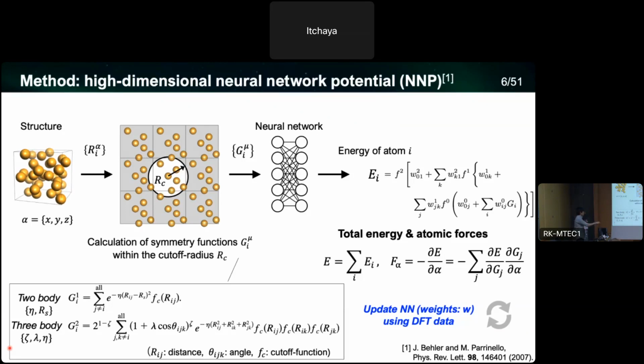And as you can see, in these functions we have several parameters like eta, lambda, zeta, and these indicate the decay factor or peak position of the functions. So we prepared different sets of parameters, and we finally get a set of different numerical values, which can be given into the neural network. Then we pass these values through the neural network, and the output we consider as the energy of atom i.